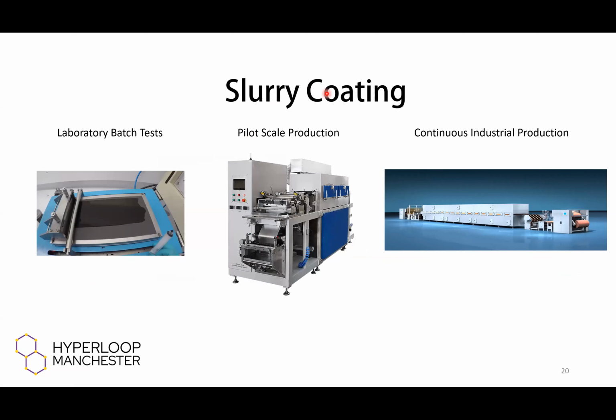Then you go into slurry coating. So you've just made your slurry, you've done the mixing. Over on the left here is a laboratory scale slurry coating process where you get this doctor blade down here, or it's a gap applicator, and that's pushed down a sheet of foil using a bar as a pusher, and then you're left with a thin coating which can then be dried.